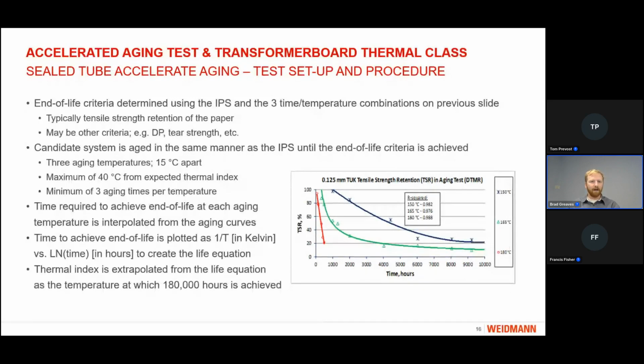You can use other criteria such as DP or tear strength, etc., but typically it is tensile strength retention. When we look at our candidate system, that is prepared and aged in the same manner as the IPS until that end-of-life criteria is achieved. So again, we have 3 aging temperatures, 15 degrees C apart, the maximum 40 degrees extrapolation from the expected thermal index, and the minimum of 3 aging times per temperature.